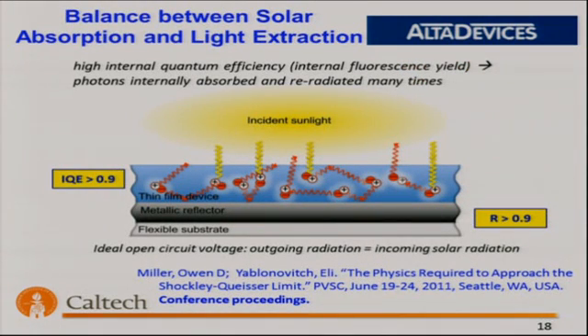But I think Eli recognized that this is certainly not the limit for efficiency. And in particular, for solar cells that have a very high internal fluorescence yield or internal quantum efficiency, high ratio of the radiative to the total emission rate, the spontaneous emission inside the semiconductor, the absorption, re-radiation, gives rise to what we call photon recycling.